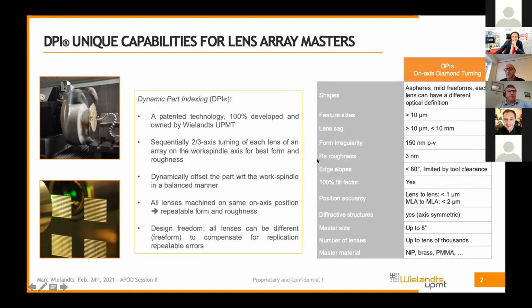And so the quality that comes out, what's very differentiating is the roughness, which is really nanometer level. It's depending on the material, but mostly we use nickel phosphorus, and then we can get to 2 or 3 nanometer roughness. We have a big degree of freedom in sizes. We say over 10 micrometer, but this can be really much bigger. In the very small micron size, we are limited by the tool, which has always a certain dimension, of course.